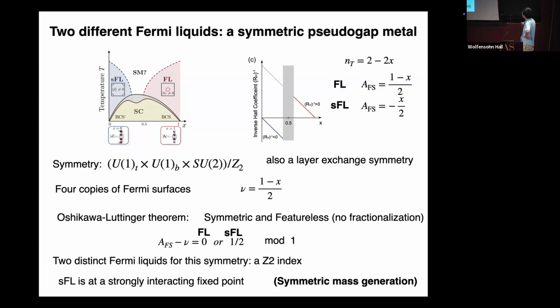Now you might think these are just two Fermi liquids, but it turns out in this case these are two different Fermi liquids. You can calculate the Fermi surface volume. One of them is 1 minus X over 2. This is the free Fermi result. The other one is minus X over 2 in this second Fermi liquid. So their difference is 1/2 per flavor. That's not expected in any mean field theory.